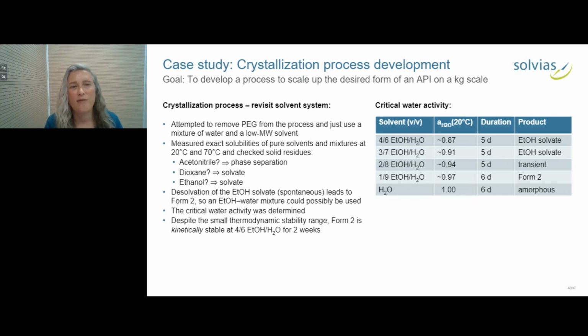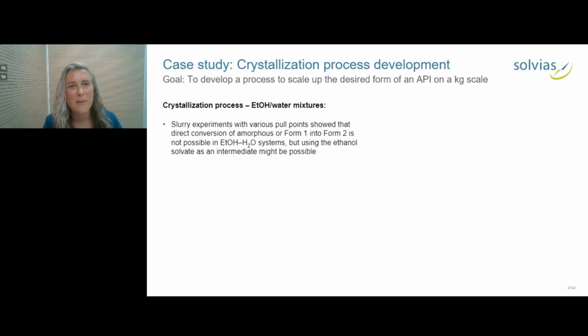But interestingly, form 2 was still kinetically stable. In this top solvent mixture, 4 to 6 ethanol water, where the ethanol solvate is stable, if you don't have any seeds of the ethanol solvate, form 2 will remain form 2 for 2 weeks. So there's enough room there to possibly develop a crystallization process. There was no strong temperature dependence, so we had to focus on anti-solvent dosage.